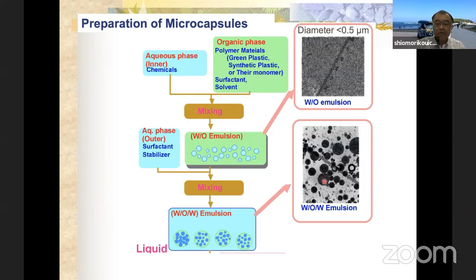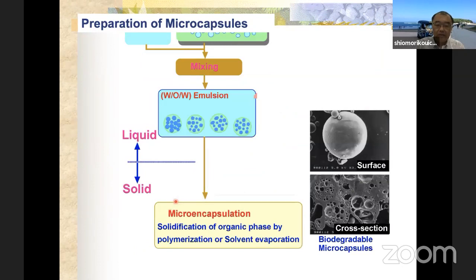After preparation of the W/O/W emulsion, we use some method to solidify the organic phase by polymerization or solvent evaporation. So the organic phase changes from liquid to solid phase. So we can get the solid particles like this, containing water droplets. The spherical droplet is the trace of the aqueous phase droplet.